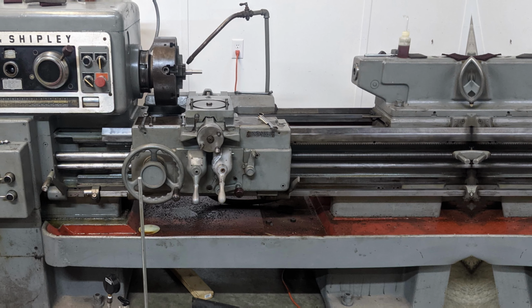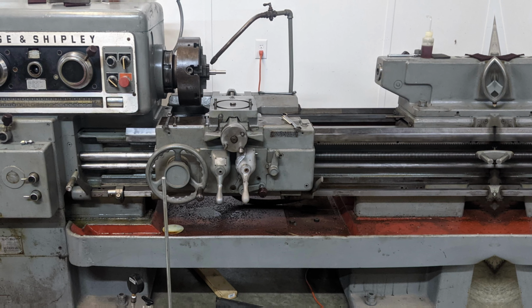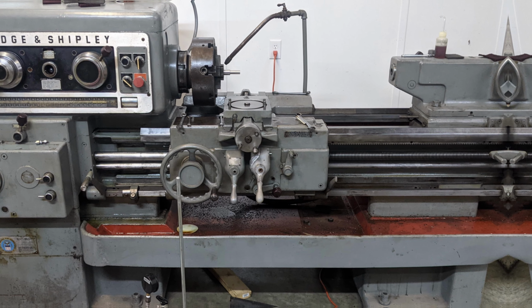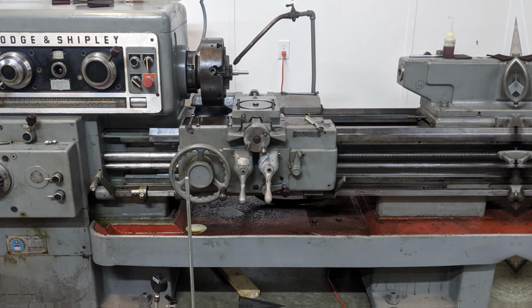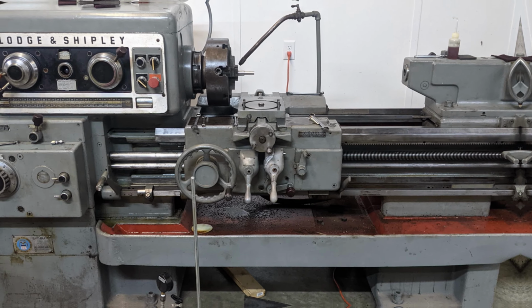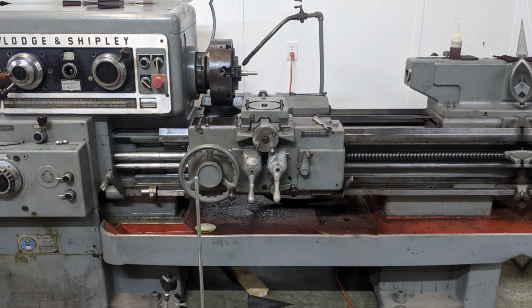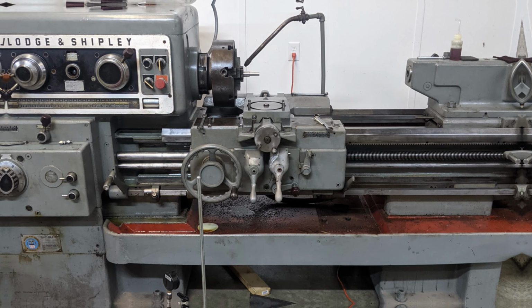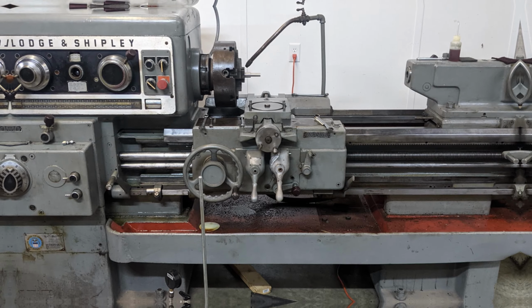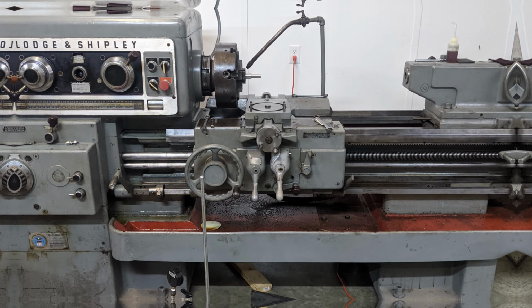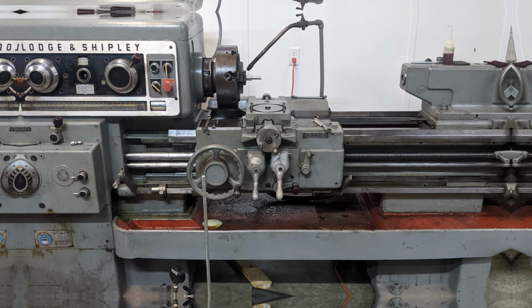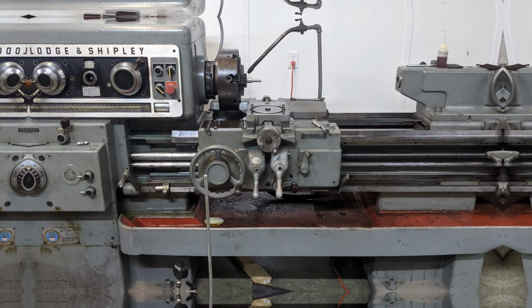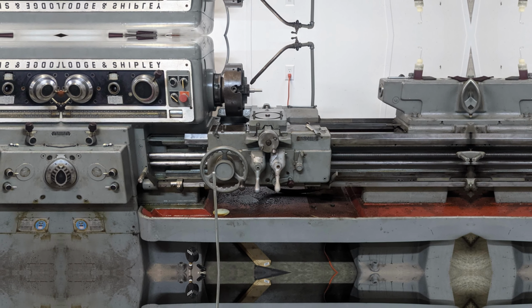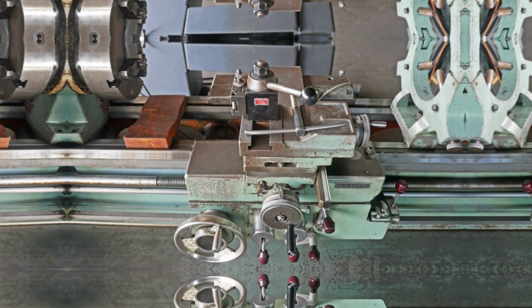The experimental program consumed 18 months and 40,000 individual cutting tests. Each test required precise alloy preparation, carefully controlled heat treatment, then actual machining operations measured for cutting speed, tool life, and dimensional accuracy. White held chromium content constant at 4%, while Taylor varied tungsten from 2% to 20% in half-percent increments. The early results validated European skepticism with mechanical brutality.